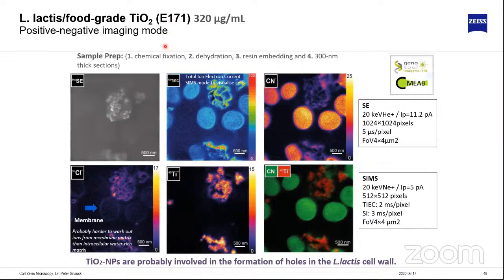And what you can do is actually you can try to feed bacteria with food-grade titanium oxide. And the first thing that you can do then is, if you did that experiment, you can fix your sample, put it into the microscope, and we can take images. So we don't see too much if we only do electron imaging here. But if we use SIMS imaging, then we start to see, so that's the total ion current, so that's not mass filtered. We can see the cells here, the bacteria, and we see some which are intact, and we see some that are not intact anymore. Some are exploded.